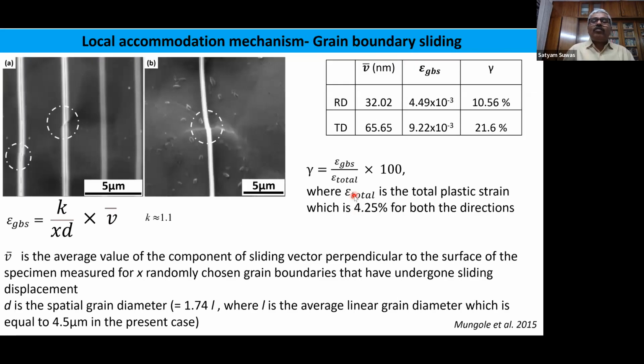To account for the local accommodation mechanism, we tried to see whether this would lead to grain boundary sliding, because this dwell fatigue phenomenon is related to the room temperature creep of the material. So we wanted to see whether there is an element of grain boundary sliding here. And then what we did is we just did the standard marker method. And after deformation, we saw how much the markers have deviated.